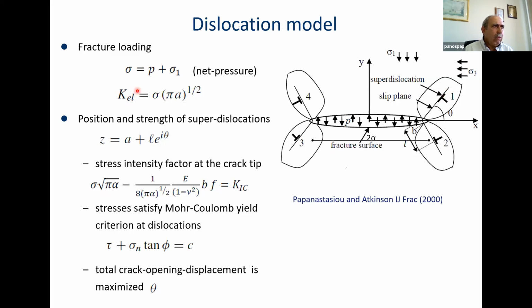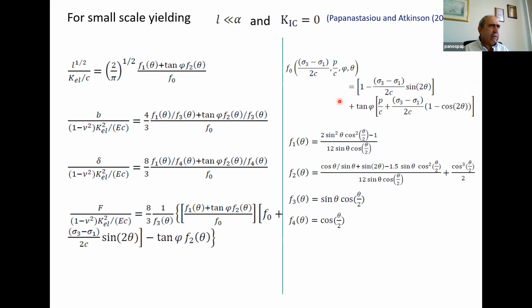And of course, we had different conditions to satisfy in order to determine the location and the strength of the dislocation. The conditions to satisfy were: the stress intensity factor at the crack tip to be equal to the toughness for propagating; at the dislocation, to satisfy the Mohr-Coulomb yield criterion; and also that the crack act to maximize the crack opening displacement.